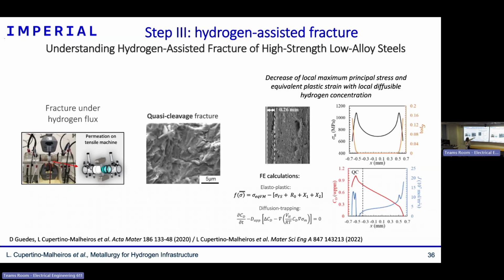And what I was looking for with this model is establishing the necessary hydrostatic stress, plastic strain, and local concentration flux necessary to fracture. So when you do this test, you basically get macro parameters: stress, strain, concentration. But by coupling with the finite element method, you can get local ones that are actually a local condition for fracture with hydrogen.